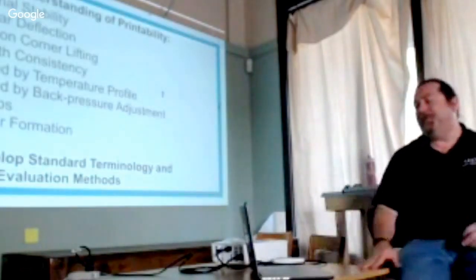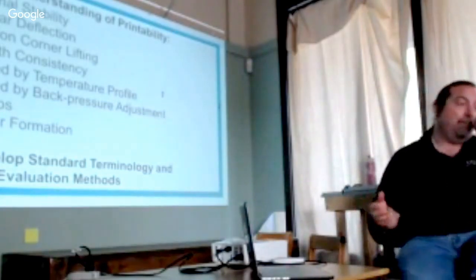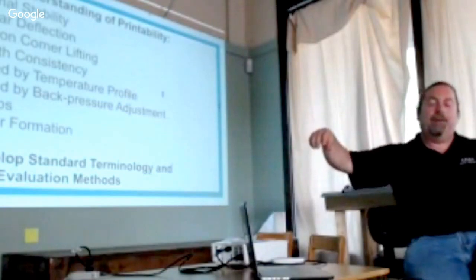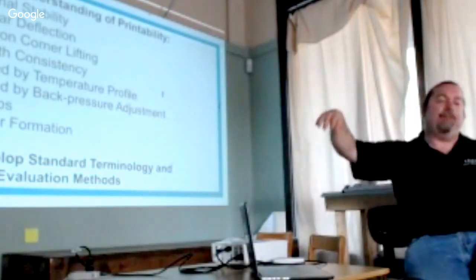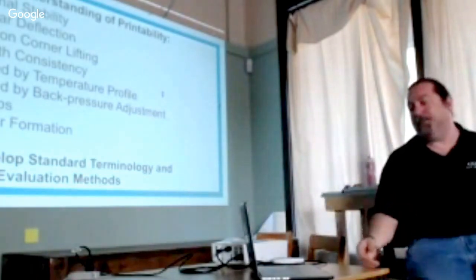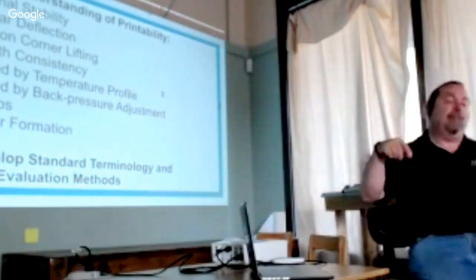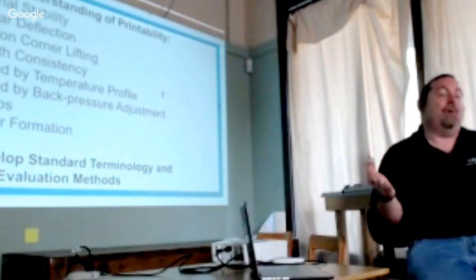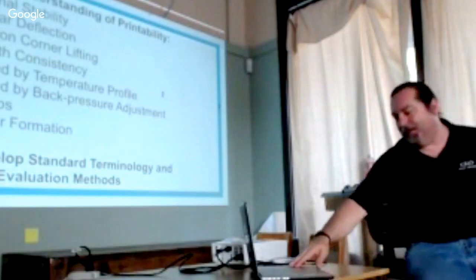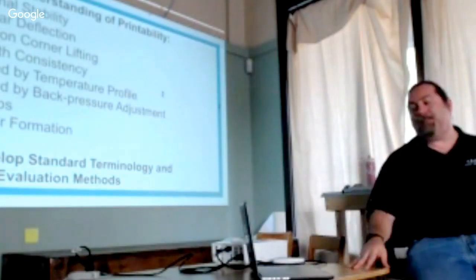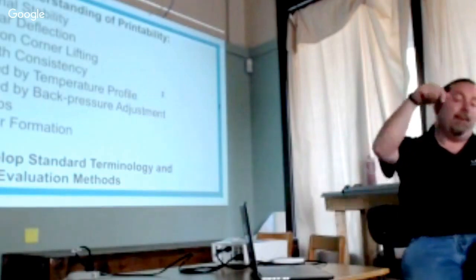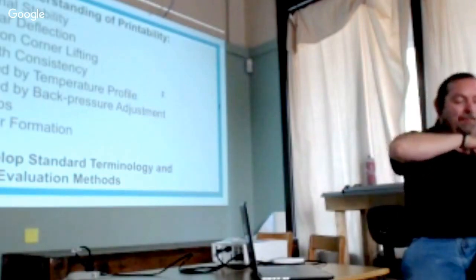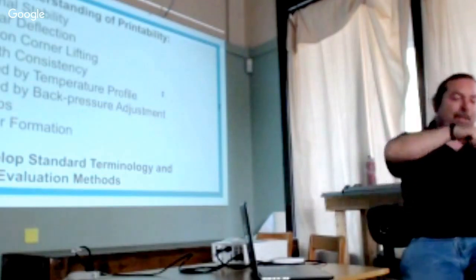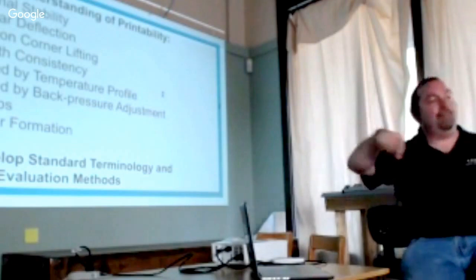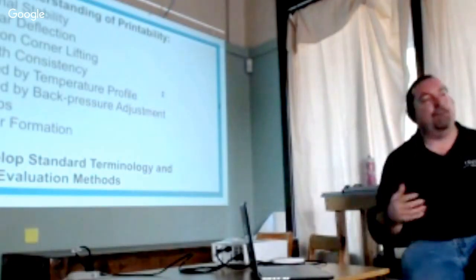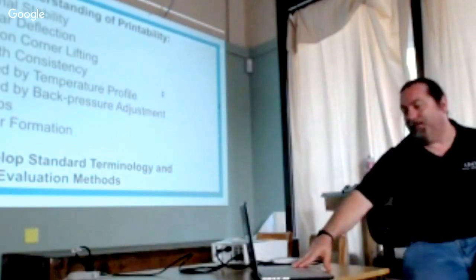So now, fundamental understanding of printability. Originally we started by printing a straight bar and measuring how much it would lift. Just the lifting of that bar is a measure of dimensional stability. Then we noticed that the hexagons that we were printing actually lifted as well, so we started measuring the hexagons. Then the bead width consistency became a real problem with some of the new materials. As the extruder would speed up and slow down, the bead width would vary, or even in a constant straight line print. Some of the materials did not behave as well as others as far as that bead width.